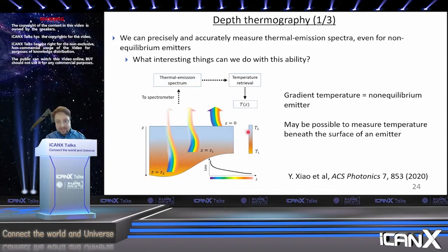So the idea here is that if you have an object that has a temperature gradient, in other words, the temperature over here on the surface may be a little colder, the temperature underneath is maybe a little bit hotter, this is actually potentially a non-equilibrium thermal emitter. And I say non-equilibrium because not all of the thermal emitters are at the same temperature. So if you have an object that's emitting from the surface and from some region below the surface, which will happen if your material is semi-transparent to infrared light, then you have this non-equilibrium thermal emitter, right?